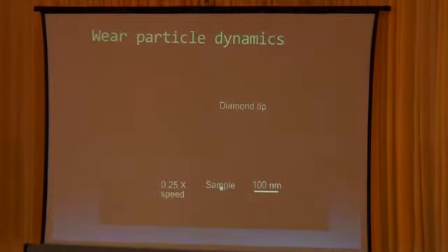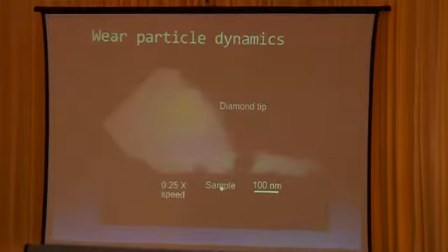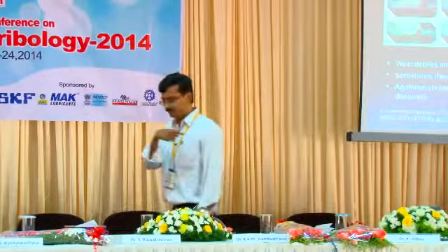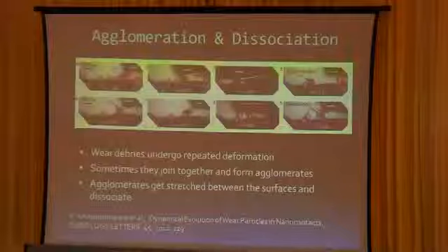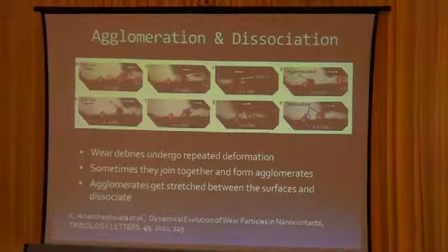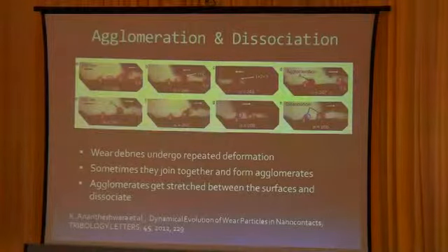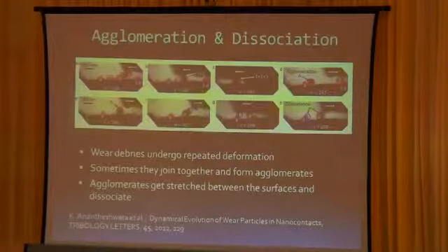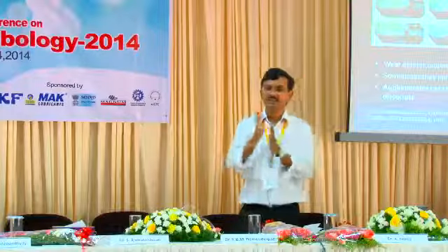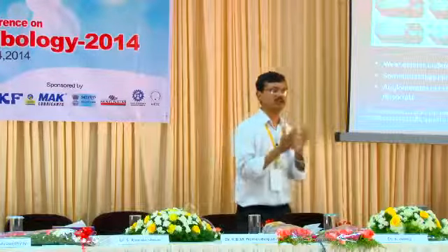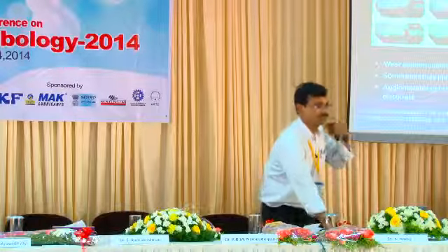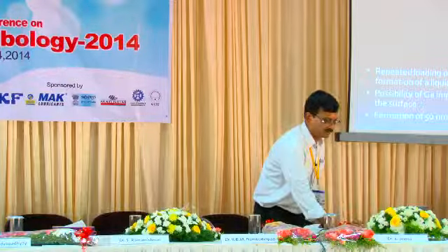You see that they are just like clay caught between your leg and the ground, or between your cycle tire and the ground. It's repeatedly getting smashed. Okay, we can study different mechanisms by which these wear particles act. Remember, these are the protective layers that are formed on the surface. Beyond this, no wear is taking place from the main material. It is this intermediate layer, third body wear, that is happening. They are absorbing all the energy that you are putting in as friction. This is the interesting thing we did.